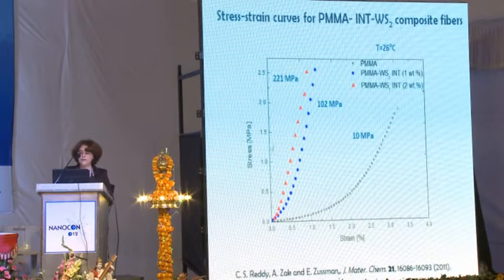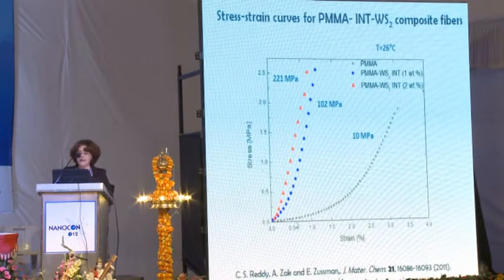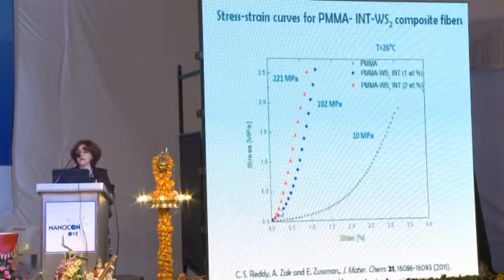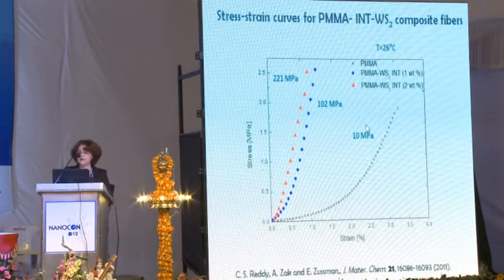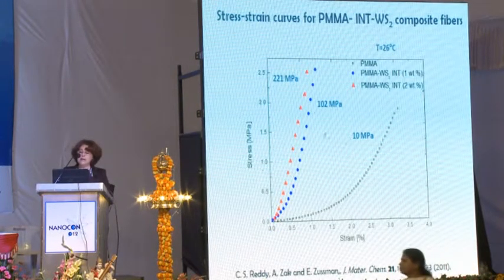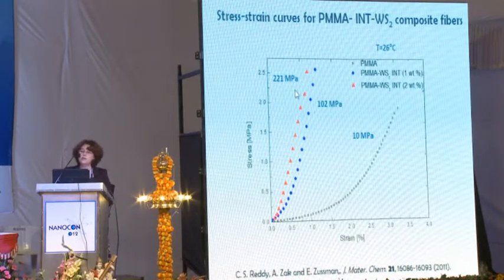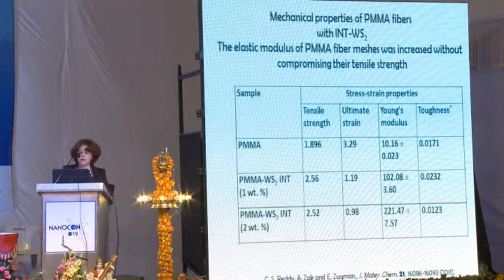Actually, you can see on this graph stress versus strain, and by calculating the slope of these curves at the beginning, where the line is linear, you can calculate the Young's modulus. You can see that compared with the neat material, the material containing nanotubes improves the Young's modulus 10 or 20 times, which is a very important and interesting result. You can also see in this table that different parameters improved: tensile strength, ultimate strain not, but Young's modulus and toughness indeed. And this is the most important parameter, which shows the energy you should apply to break this material. And you can also see here the importance of the concentration when we prepare composites.